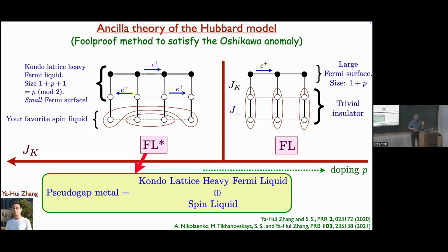Now, Oshikawa would tell you, for the Hubbard model or its related ancilla model, this violates the Luttinger value. So there must be a spin liquid. And that's the beauty of the ancilla construction. You don't have to even know about Oshikawa. All you have to know is that you added a trivial set of ancillas. There's a spin liquid, that's the bottom layer. It is there. And so you're obeying Oshikawa. And this spin liquid is exactly at filling 1. I mean, it has the anomaly of exactly 1 electron per site.